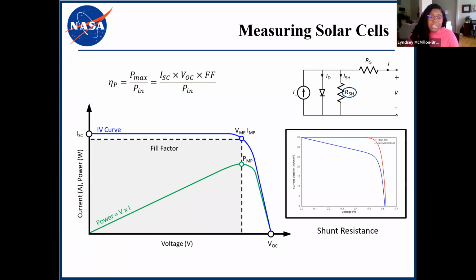So if you look at a cell with significant shunt resistance, we would have an IV curve that looks something like this. Shunt resistance is typically due to manufacturing defects that cause power losses by providing an alternative current path. And this diversion reduces the amount of light generated current that flows through the junction, and therefore we see a decrease in voltage.